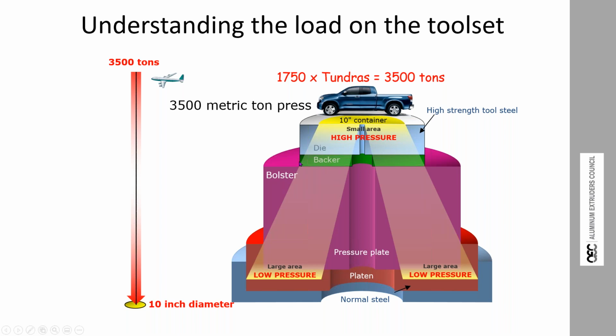But if we were to put a wedge in under here, then this side would take very little pressure and this side would have much more pressure. And you can say those bolsters, hell, they're H13 steel. They're 1.5 feet thick. They ain't going to bend. Well, I can tell you, a stack of Toyota Tundras, 3,500 tons, that'll bend that tool. That will damage it.